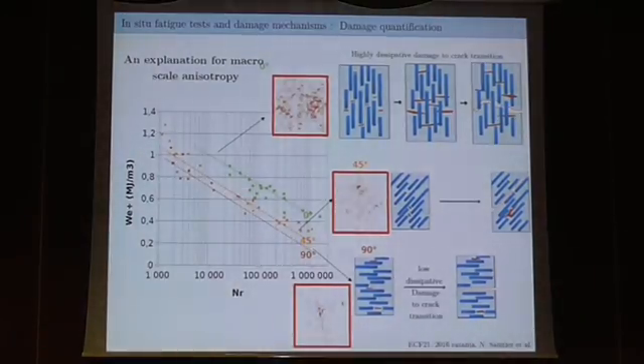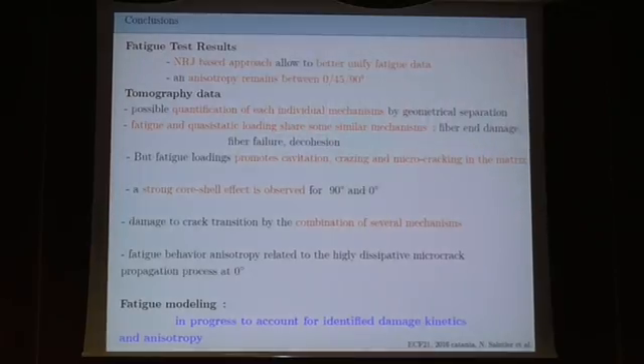So finally, if I go back to this, and I will conclude on that, if I go back to the macroscopic behavior and the anisotropy that you observe, the anisotropy is due to the fact that you can put much more damage in your 0° angle specimen. So you put much more energy to reach the same fatigue life. And you have a much more dissipative process here in the final crack propagation process. So that's really linked to the degree of dissipation that you need to put into your specimen to reach the failure of the specimen and experimentally match the observation.